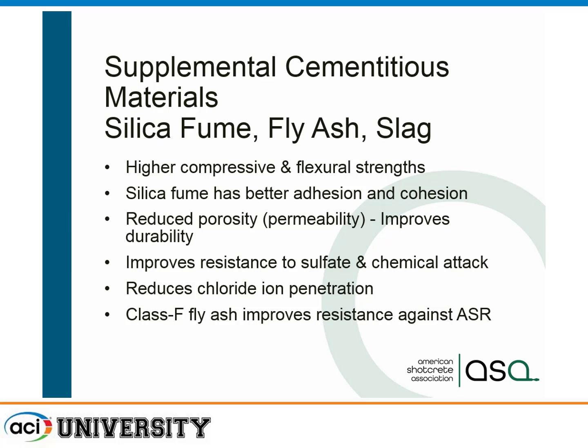We also use fly ash. Fly ash increases our pumpability. A lot of times if you have a mix that's not working really well with just Portland cement, you can add fly ash and it'll help to slick the line a little bit more. And we've used mixtures, I've heard, up to 70% slag. So we are very sustainable in using recycled materials. And most of these are good for shotcrete, good for concrete, reducing permeability. Class F fly ash helps mitigate problems with ASR.